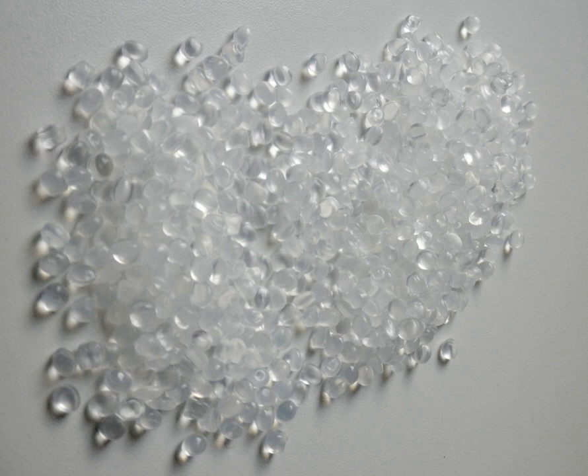PE can become brittle when exposed to sunlight. Carbon black is usually used as a UV stabilizer. Polyethylene burns slowly with a blue flame having a yellow tip and gives off an odor of paraffin, similar to candle flame. The material continues burning on removal of the flame source and produces a drip. Polyethylene cannot be imprinted or bonded with adhesives without pretreatment. High-strength joins are readily achieved with plastic welding.